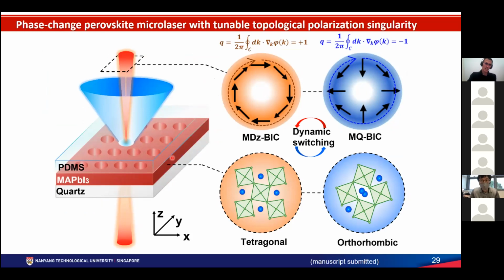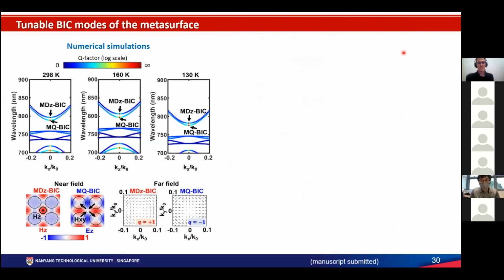Another interesting thing is that the perovskite can actually undergo a phase transition. So once you modulate the phase transition of the perovskite, you will be able to see that the metasurface, which supports more than one mode, will start emitting laser light with a polarization vortex that has a winding number, a topological charge, of -1.